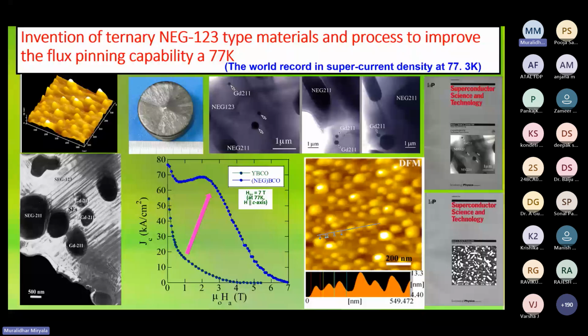When we made a magnet, the critical current density, you can see in the bottom figure, the x-axis is the magnetic field. At 4 Tesla or 3 Tesla it is almost zero in the YBCO system. But in the case of what we made, the irreversibility field is very high, around 7 Tesla. We created nano pinning using smaller Gd211 nanoparticles, non-superconducting, which pin in the high magnetic field. As a result, one can make a very high critical current density.